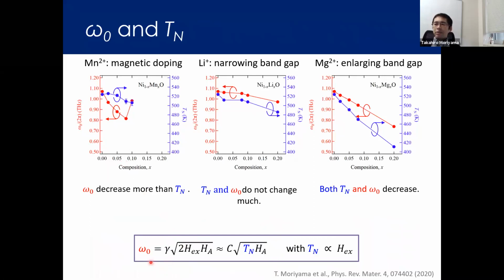So here we assume the Néel temperature is basically proportional to the exchange field. We have this quadratic relation between the omega 0 and Néel temperature like this. Based on this relationship, comparing the omega 0 and the TN reduction for each doping concentration, we can say from this data that the dominant effect of the manganese doping, which is a magnetic doping, is a reduction of the HA. And for the Mg doping, the dominant effect seems to be reducing the exchange field. And for lithium, we don't have much conclusion because Néel temperature and omega 0 do not change much.